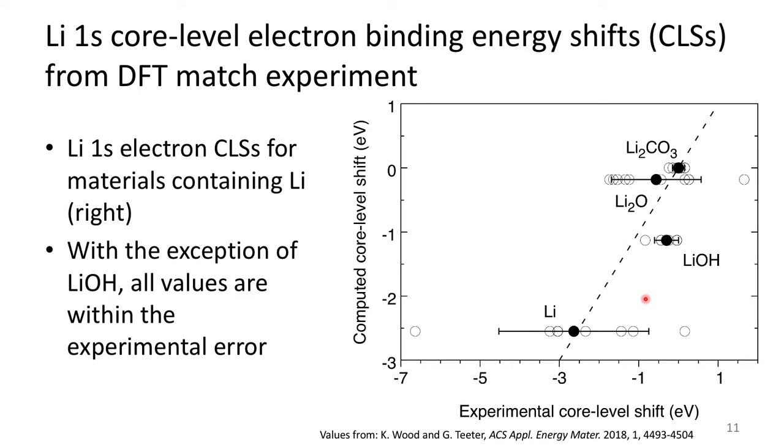In this plot, I show the standard deviation in the experimental data set by error bars. And as you can see, with the exception of lithium hydroxide, the computed data is well within the experimental standard deviation of each phase. And in particular, there's very good agreement for lithium metal and lithium oxide, which is really what matters for the current study.